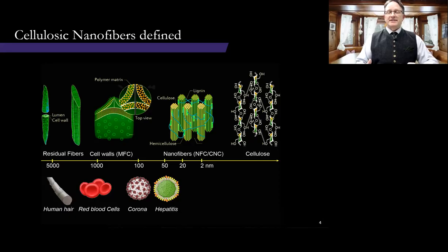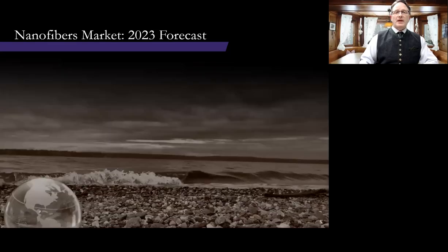Hepatitis is 50 nanometers in diameter. Nanofibers reside in the 50 to 2 nanometer range, and they can be divided into two categories. We have nanofibrillated cellulose, which retains the amorphous and crystalline regions in the fibers. And then we have crystalline nanocellulose, in which the amorphous regions have been removed. So I presented both an environmental and a functional justification for utilizing nanofibers.